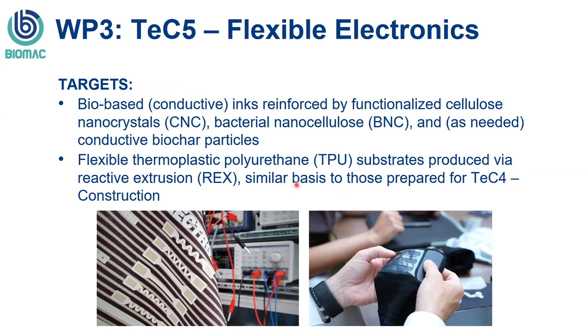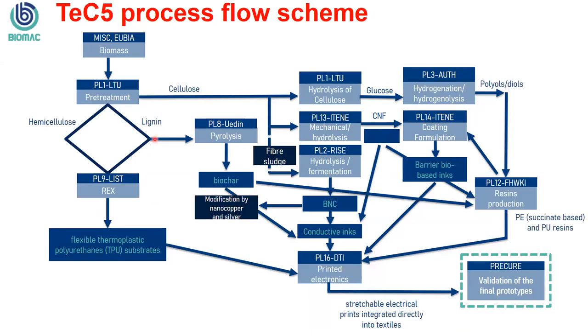And then the thermoplastic polyurethane substrate forms the basis for these. And so to show where these are all coming from, this is the process flow scheme. Biomass is pre-treated and converted into a variety of different streams as always. So we have hemicellulose and lignin potentially used for reactive extrusion in the formation of, again, non-isocyanate polyurethanes, just as in the previous case. We have cellulose here being used in a variety of ways. We can break the cellulose down to monomers, and we can use those monomers to create polyesters and eventually polyurethanes. So think back to the first test case where we had reactive polyurethane oligomers based on polyesters that we were using as a basis for this UV type 3D printing application.